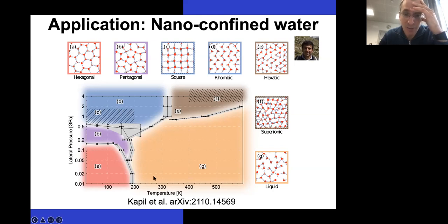We can work out the melting temperatures. So we see that depending upon the applied pressure, we have a melting temperature for this nano-confined ice that varies from 200 Kelvin up to several hundred degrees higher. There's a regime where the water molecules dissociate and we have a superionic phase. And it's an incredibly rich phase diagram